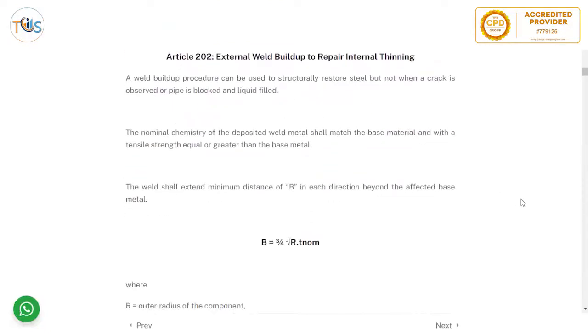Article 202, weld build-up procedure, can be used to structurally restore steel, but not when a crack is observed or the pipe is blocked or liquid filled. So you can build up the thickness by welding it, but not when there is a crack, because the crack can break through that. So that crack needs to be removed, and the tip first blunted by drilling at the ends, or the crack totally removed and tested, and make sure that the crack is removed, like MT/PT tested after removal of the crack.